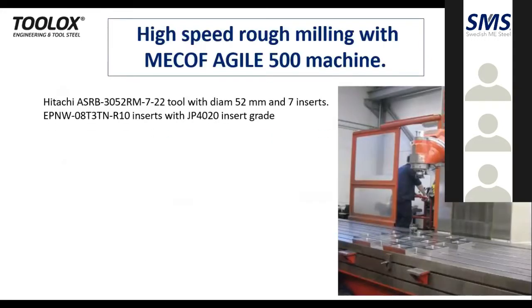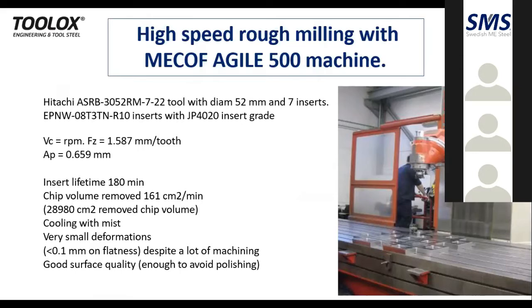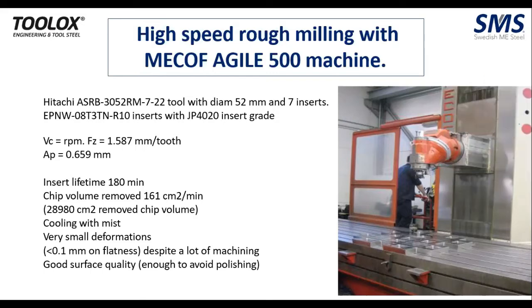Yeah. So this is high-speed milling, which is happening. Here, this insert has run for 180 minutes, which is close to 3 hours. We have removed an enormous amount of chip during this, 28,980 centimeters square. Even after this extensive milling, the deformation level is very, very small. It is less than 0.1 on flatness. So even after extensive machining, the surface quality still remains great, to the extent that you do not require any additional polishing.